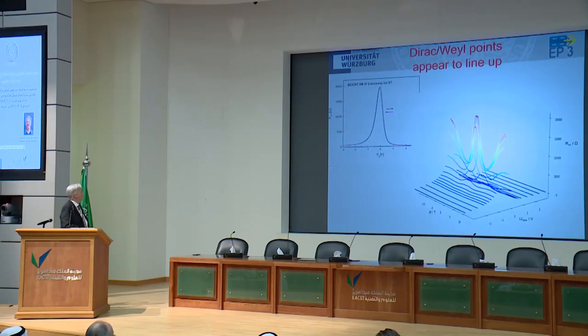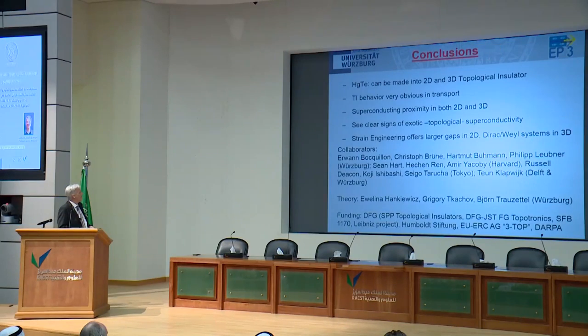This is a zero field gate sweep, so we really see that the Dirac points, we can directly define these in our material. And you can also show that actually this negative magnetoresistance, this chiral anomaly, only shows up when the Fermi level is really at the Dirac point. What we're doing now, of course, is inducing superconductivity in these systems because you expect very interesting superconducting pairing from these Dirac points in your band structure.